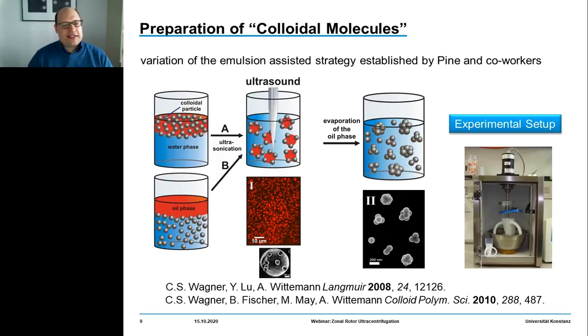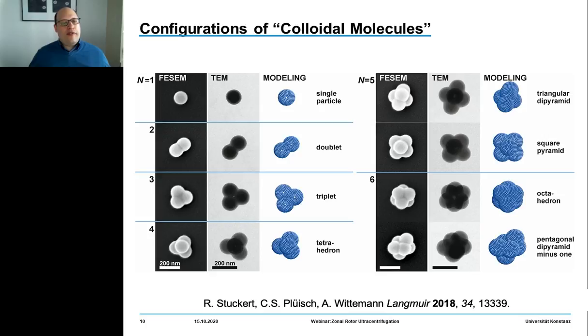The emulsion droplet serves as a template for assembly into clusters. If we now evaporate the dispersed droplet phase, we create strong capillary forces which make the particles come together and assemble into clusters of well-defined geometries.